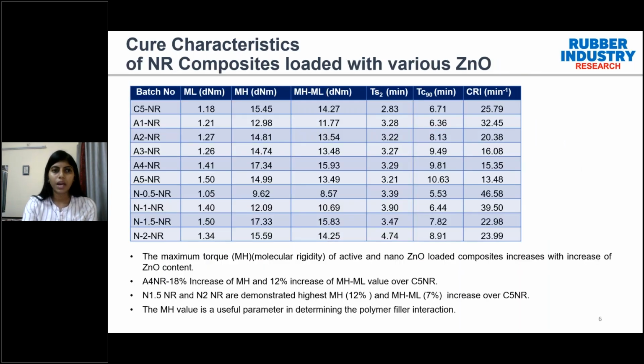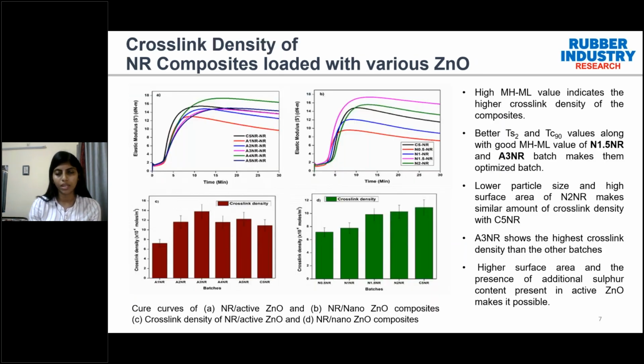The cure characteristics give the processing properties of the compound. The torque values, like the MH value and MH minus ML, the delta torque, also give the polymer-filler interaction. Here we can see that the MH value of the active and nano zinc oxide loaded composites increases with the increase of zinc oxide content. From the MH minus ML value, which we call delta torque, we can see that the higher the delta torque, the higher the cross-link density. Comparing the elastic modulus with time curve and the cross-link density of the compounds, the trend was the same: whichever compound has the highest delta torque shows the highest cross-link density.